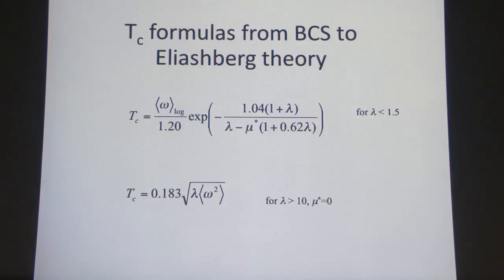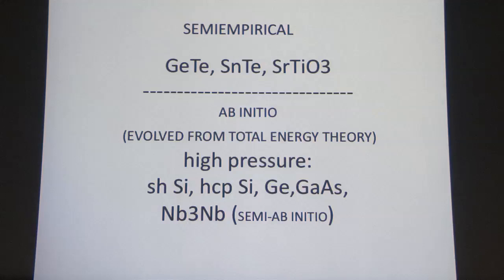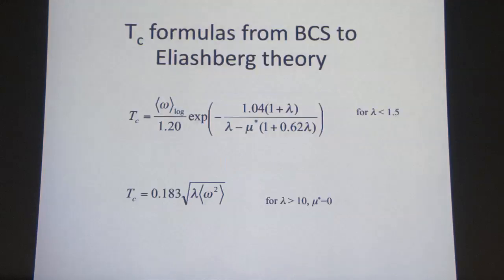And in fact, it gets even simpler. If lambda is really strong, if you want to make a really high TC superconductor, let's say room temperature, which is the holy grail for this field, everyone is trying to get the higher temperatures, then all you need to know is the electron-phonon strength and the phonon frequency. And it's just the square root of that.